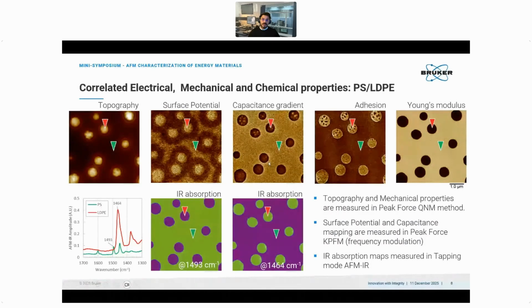Now, at the same time, on the same sample, since we are basically using peak force combined with Kelvin probe force microscopy, which is the surface potential measurement, the peak force allows us, because it's based on quantitative nanomechanical mapping, to get at the same time the mechanical properties variations, like the adhesion. So the adhesion here is, as Tobias showed, the adhesion between the tip apex and the top surface of the sample. And the Young's modulus, which is the modulus of elasticity. Obviously here, clearer is higher and darker is lower for all these color scales. Now, these things you can get on any Bruker system that is equipped with these peak force QNM and peak force KPFM modes.